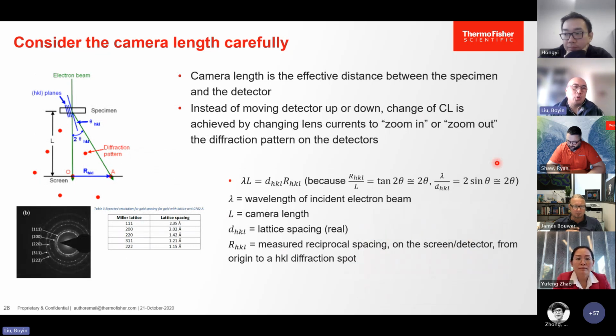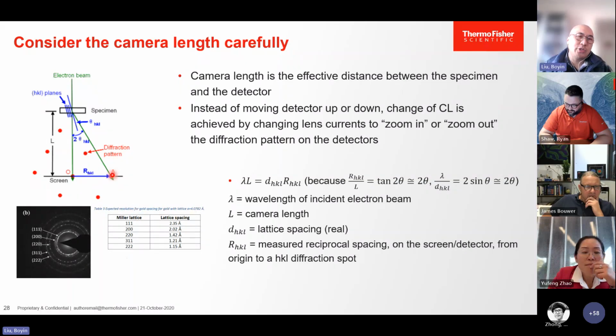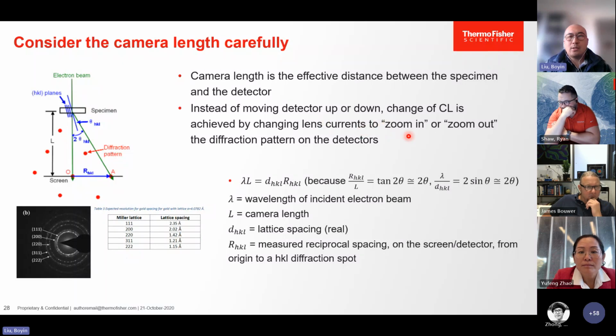So another thing is to decide your camera length for the sample. So, what is camera length? Camera length is actually the distance between the specimen and the detector. But on the TEM, it's physically impossible to move the detector up and down. Sometimes the camera length can be 3 meters, and there's just no room to fit that in a TEM. So instead of changing the detector position, the detector stays there, and we change the lens current to create a zoom in or zoom out effect to achieve the effective camera distance.